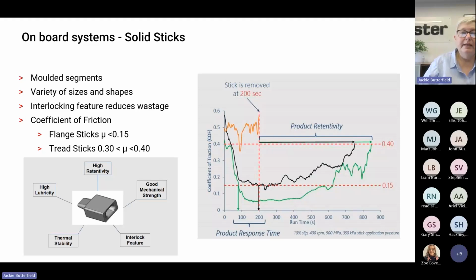Again, we can test sticks in a laboratory. And on the right-hand side, you've got an example of a twin disc test. So this is measuring effectively the coefficient of friction that you get with the stick, adding the stick for a specific amount of time, in this case 200 seconds, and then removing the stick and then plotting the coefficient of friction and how that material is exhausted in the wheel rail interface. So you want the stick to give a low coefficient of friction, so below this red line, below 0.15. And then you want it to last as long as possible, so the product retentivity.